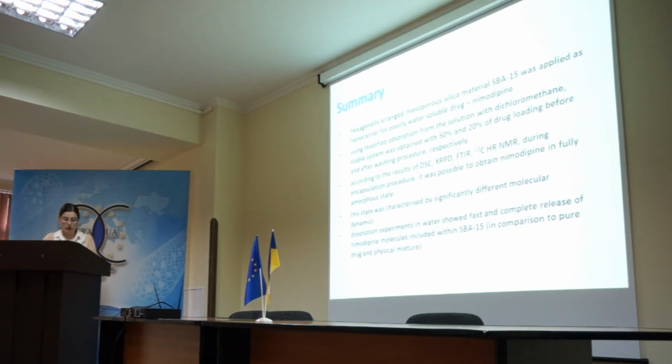According to the results of several methods, during encapsulation, it was possible to obtain nimodipine in amorphous state, and this state was characterized by different molecular dynamics than for crystalline drug. And some dissolution experiments showed a fast and complete release of nimodipine included within the SBA-15.